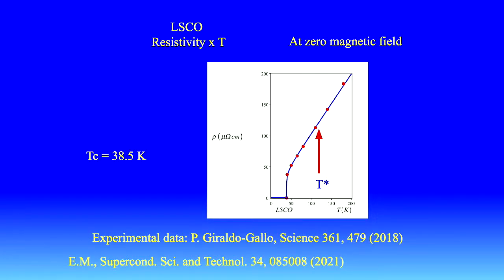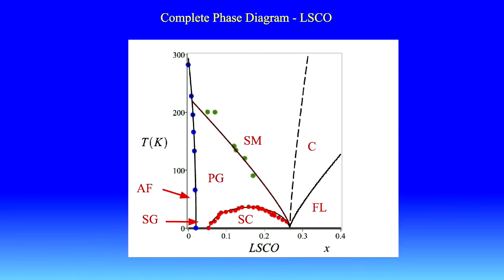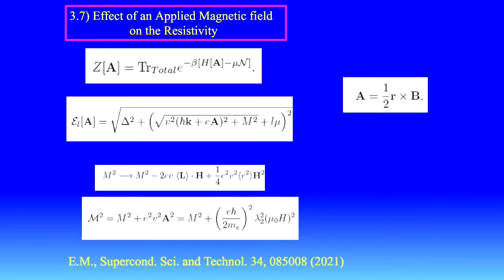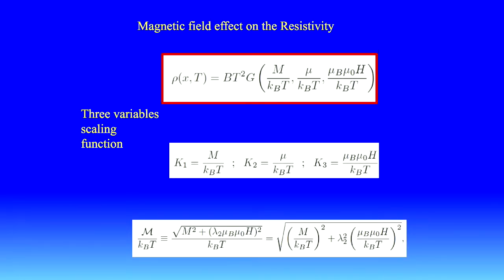Again, you see resistivity of LSCO versus temperature at zero magnetic field for this TC. So you see that the phase diagram is coming alive, because now we have analytical expressions for all of these curves. Now, finally, applied magnetic field. We introduce this A, and we have a similar expression. Now we have three scaling variables.